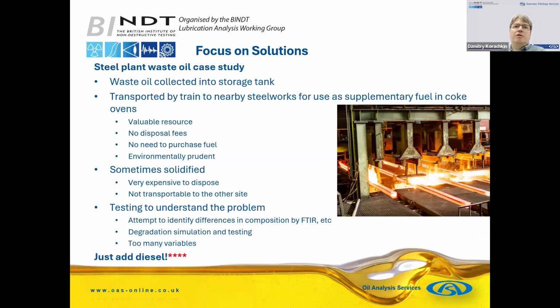And then finally, when a lab is trying to help, they may be able to give you advice not only on what the cause of something is, but sometimes a solution. We have spent some time investigating a situation where some waste oil was turning into a solidified gloop, which could not be used, and then it became very expensive to dispose. Whereas when it stayed liquid, it could actually be used as a supplementary fuel in coke ovens. So we performed a lot of testing, and we just could not identify what the problem was, whether it was specific contamination, whether it was just a different initial product coming in. There were just too many variables at the time.